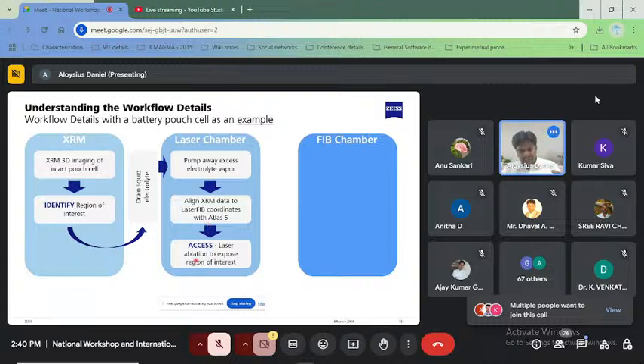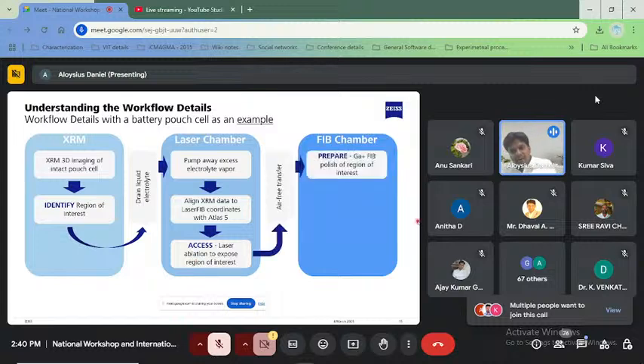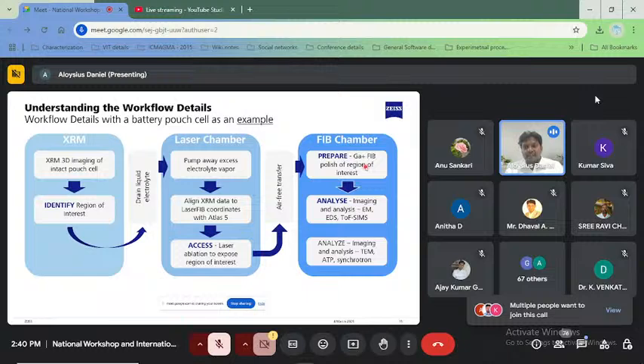Once the region of interest is exposed, it moves inside the ion column or the FIB chamber, and then we use the gallium ion for preparing and polishing, and then it is taken for all these analytics like EDS, WDS, EBSD, TOF-SIMS, or it can be used for TEM and APT analysis as well. So this is a quick workflow, how it works.